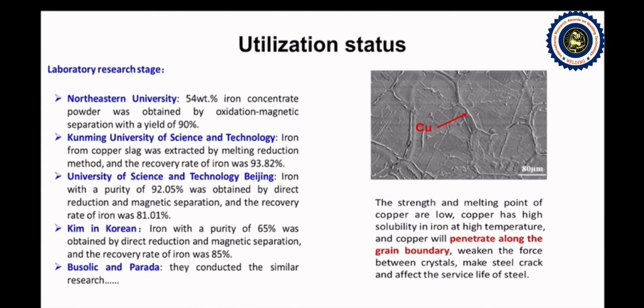Next, let's talk about the utilization status of copper slag, especially the recovery of valuable metals. In Northeastern University, 54% iron concentrate powder was obtained by oxidation and magnetic separation with a yield of 90%. In Kunming University of Science and Technology, iron from copper slag was extracted by the melting reduction method, and the recovery rate of iron was 93.82%. There are other similar research. However, all of them are in the laboratory stage, and the pure iron obtained cannot be directly used in steel making because of its high copper content.